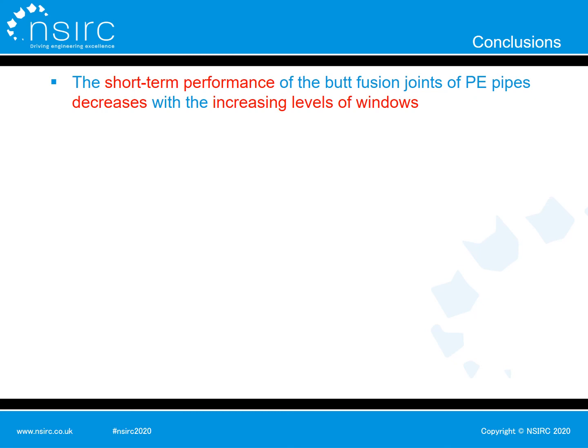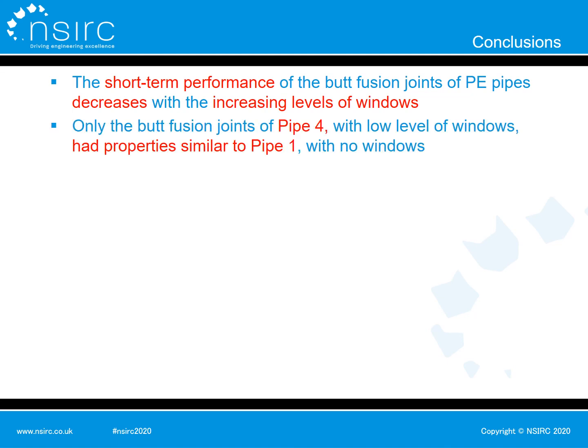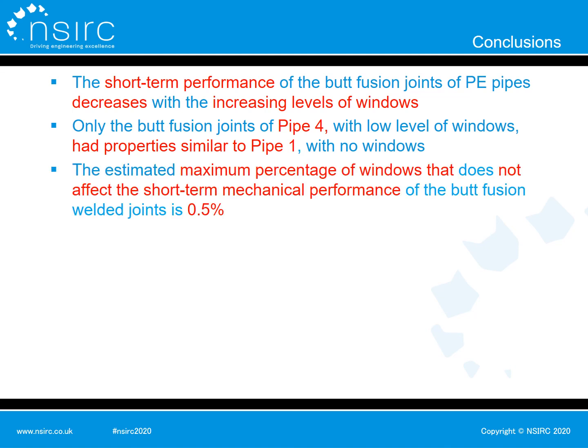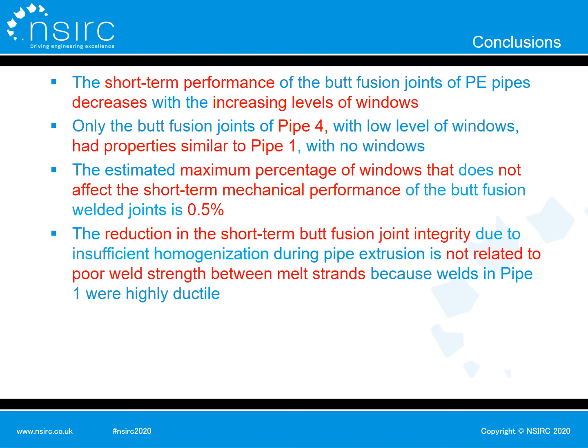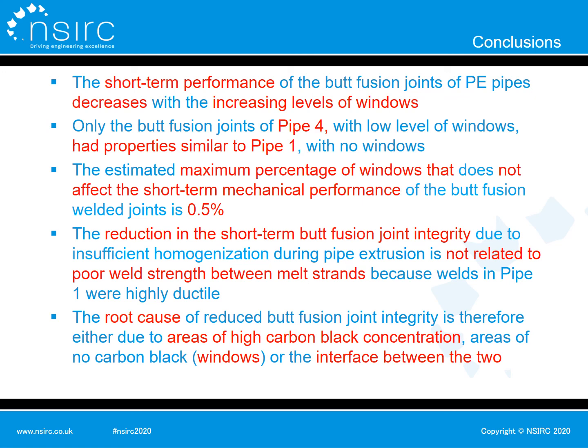In conclusion, the short-term performance of the butt fusion joints of polyethylene pipes decreases with the increasing levels of windows. Only the butt fusion joints of pipe 4 with low level of windows had properties similar to pipe 1 with no windows. The estimated maximum percentage of windows that does not affect the short-term mechanical performance of butt fusion welded joints is 0.5%. The reduction in the short-term butt fusion joint integrity due to insufficient homogenization during the pipe extrusion is not related to poor weld strength between melt strands, because welds in pipe 1 were highly ductile. The root cause of reduced butt fusion joint integrity is therefore either due to areas of high carbon black concentration, areas of windows, or the interface between the two.